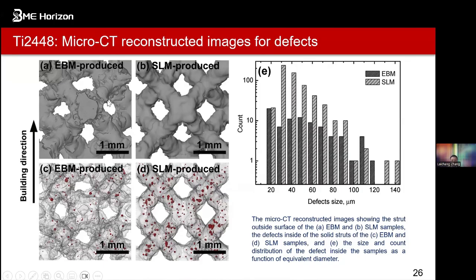Also you can see from figure C and D, they show the locations and the distributions of the defects. They are marked in red color inside the solid strut. You can see a lot of the red color. That's the defects inside, and also this is the distribution of the parts. As you can see, nearly all the defects in the EBM parts are in spherical shape, while those in the SLM have an irregular shape, and some even large defects display a crack-like shape. So now, of course, we can summarize these parts.